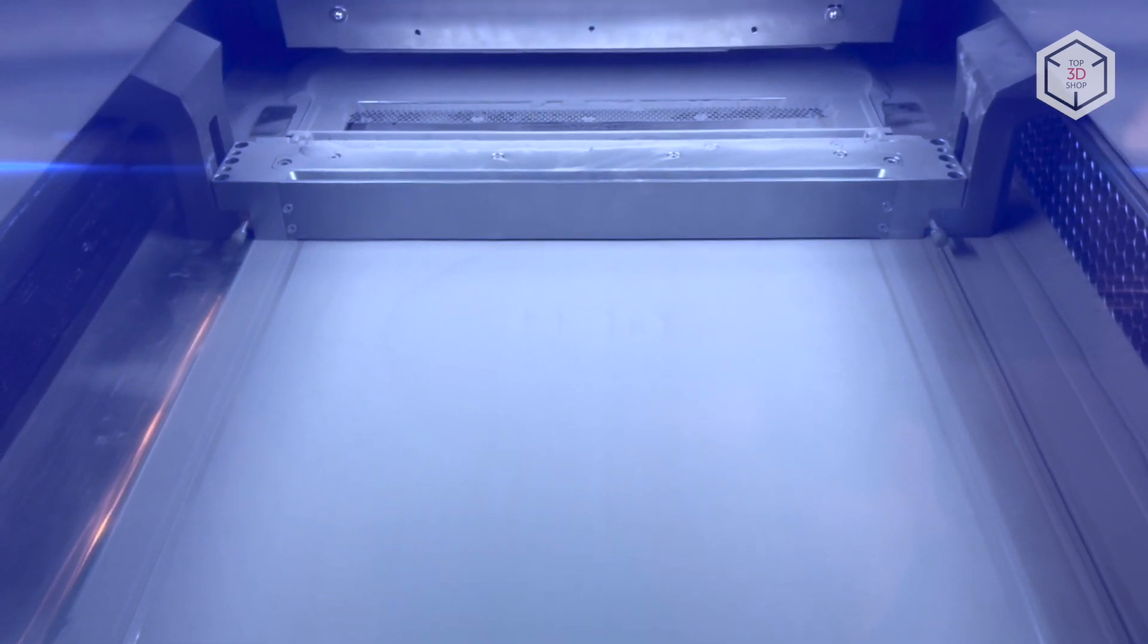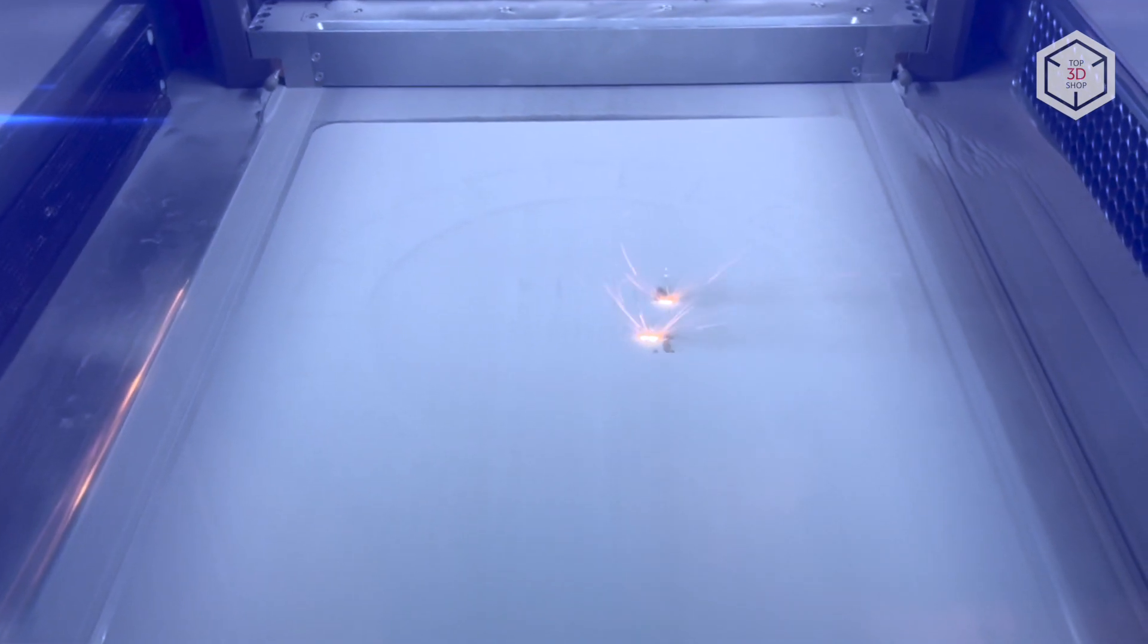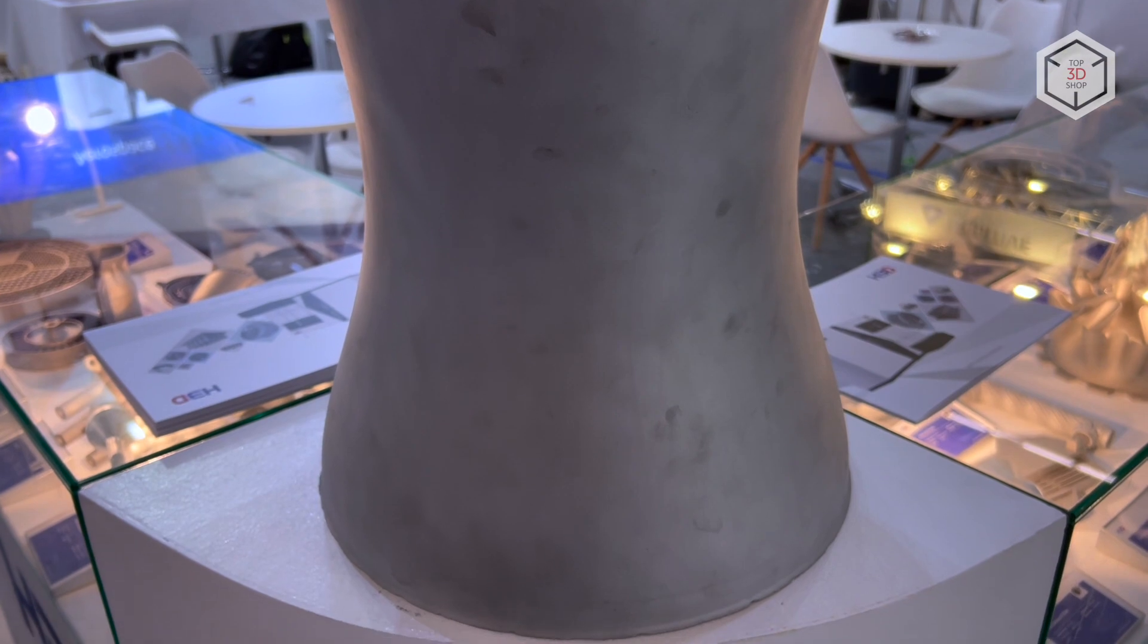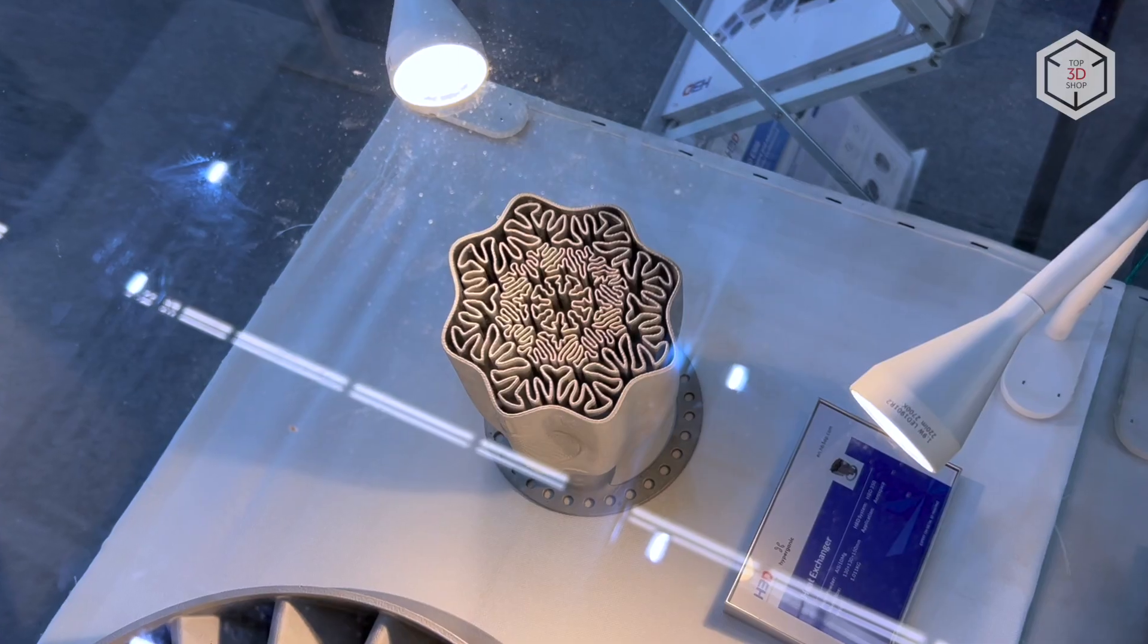Other specs include the width of the scanned area from 70 to 100 microns and layer thickness from 30 to 100 microns. The device can print large parts of high quality and precision for use in the most demanding components of industrial equipment and aerospace technology.